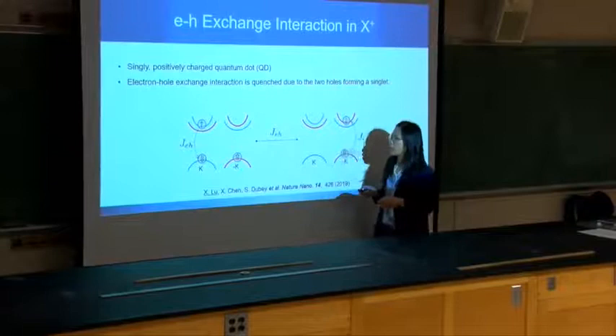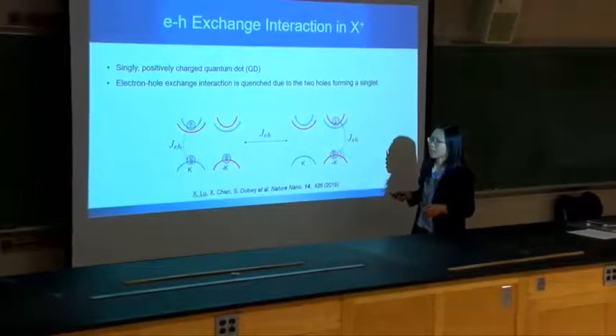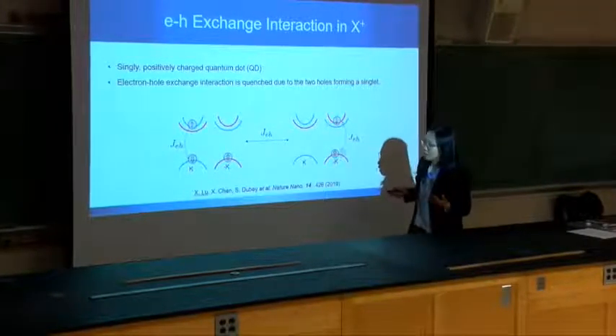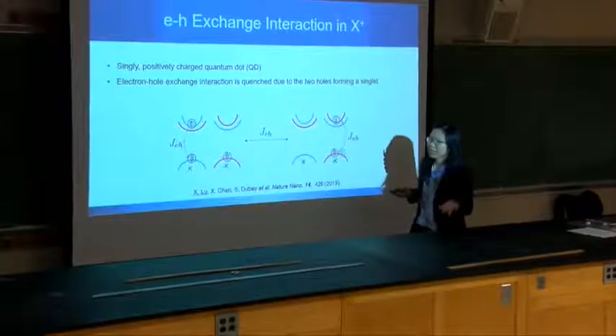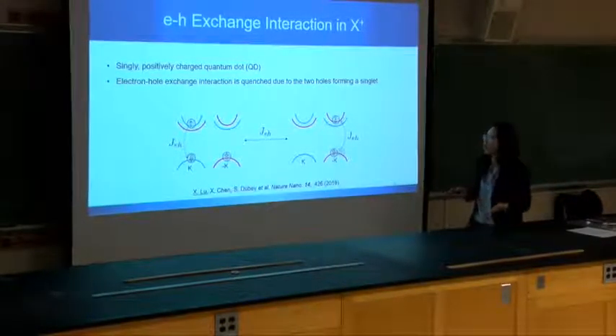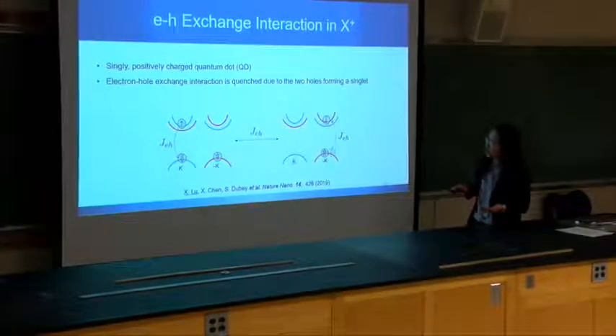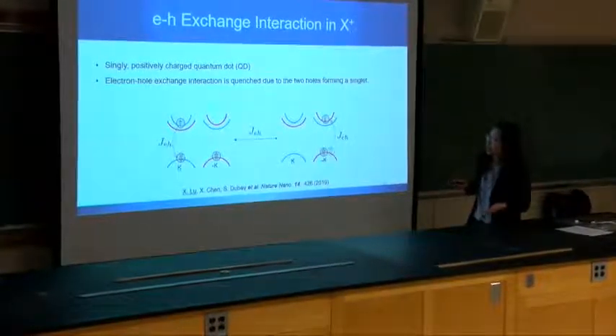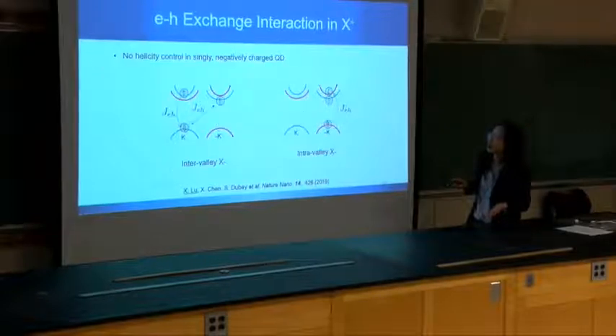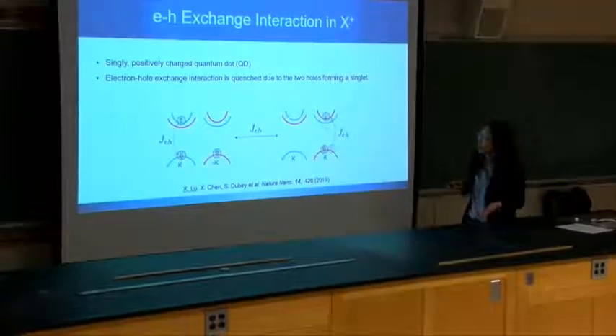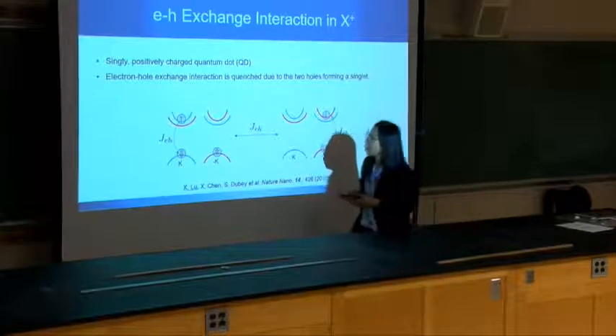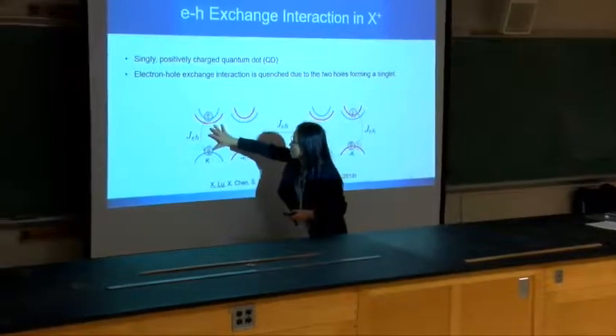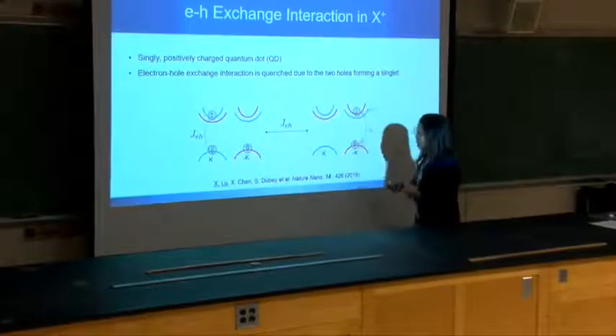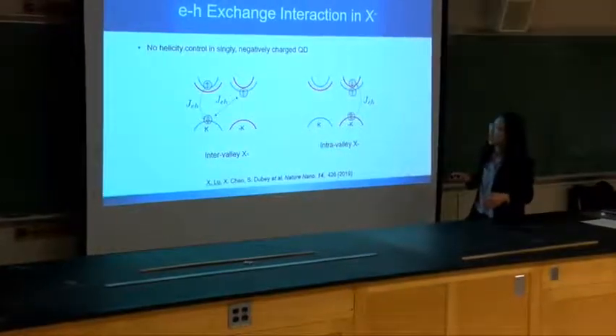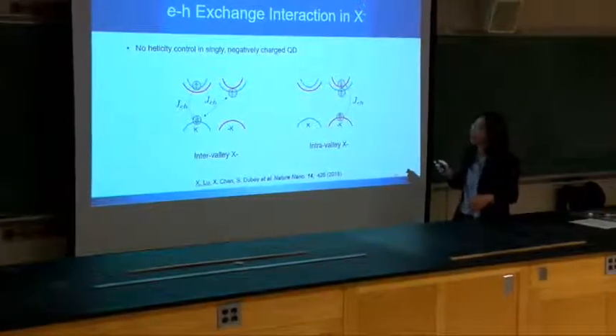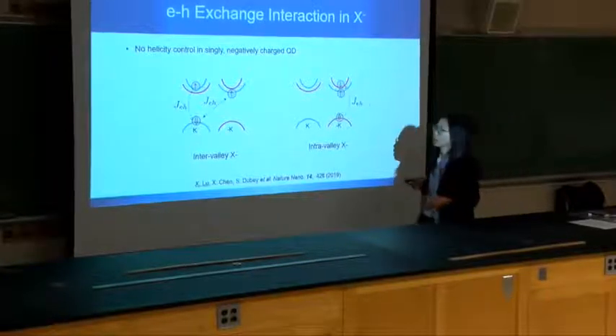But here, as the two holes form a singlet state, the electron will not see a net exchange interaction. So in this way, the exchange is quenched. And that's the singly positive charged quantum dot. So if we use light to optically initialize it, it should stay robust because exchange is quenched. So how about a negatively charged quantum dot or negatively charged single photon emitter?